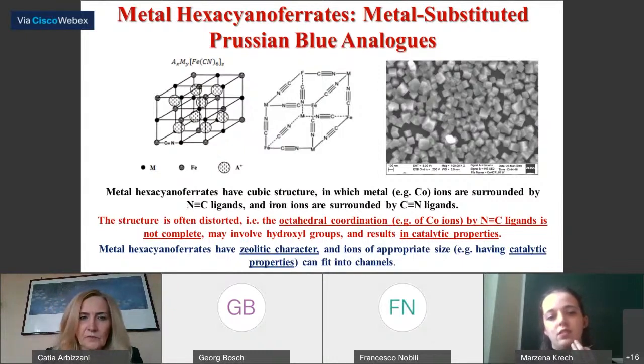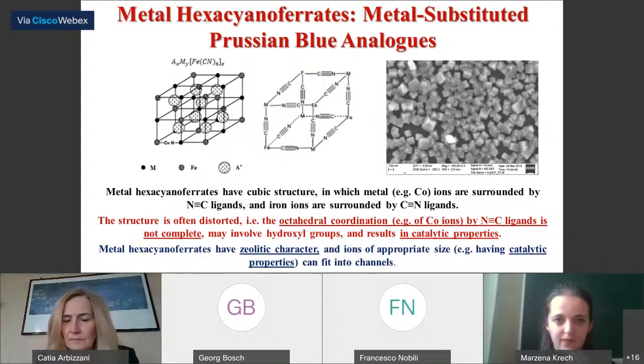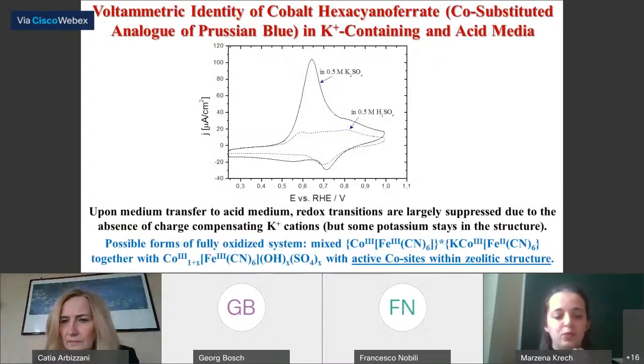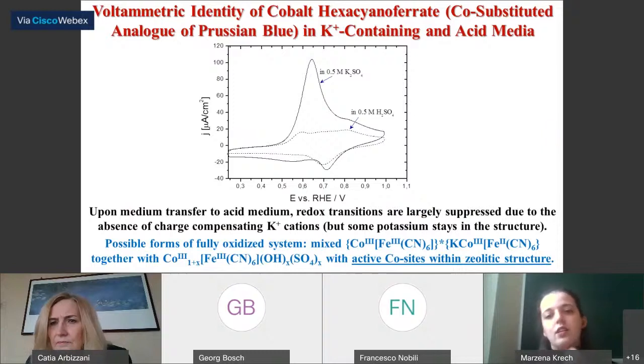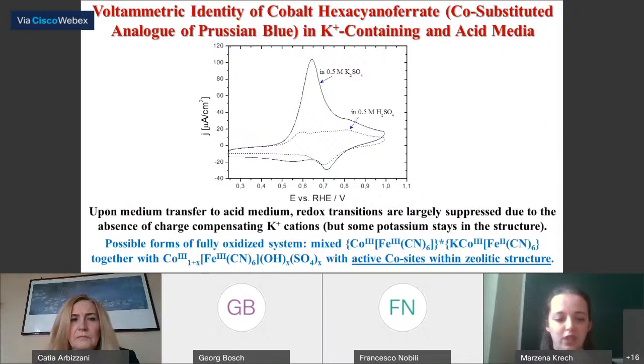These compounds have zeolitic character and only ions of appropriate size, for example having catalytic properties, can fit into the channel. This graph shows the difference between measuring cobalt hexacyanoferrate in two different environments. Upon medium transfer to acid medium, redox transitions are largely suppressed due to the absence of charge compensating potassium cations, but some potassium stays in the structure. Possible forms of fully oxidized cobalt hexacyanoferrate include also structures containing potassium and catalytic cobalt in zeolitic channels.